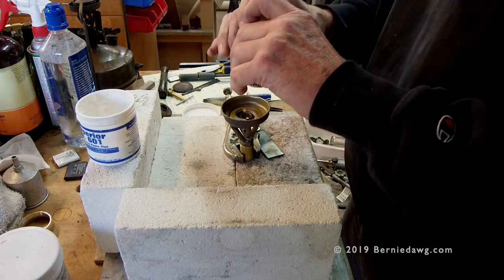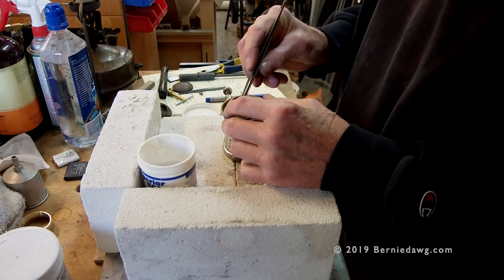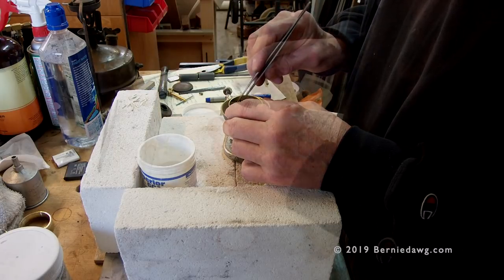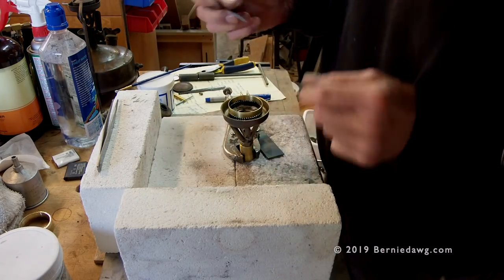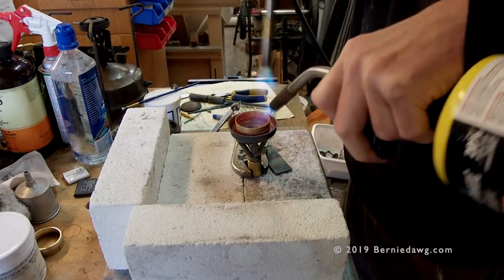I carefully placed the ring inside the burner bowl and used a small metric ruler to make sure it was centered. Then I took small cut pieces of brazing filler wire, dipped them in flux, and placed them along the bottom edge inside the ring. One last check for measurements to make sure everything was perfectly centered and aligned — you only get one shot at this. Then I grabbed a couple of torches, heated it up, and got the silver braze filler to melt and flow, holding the ring into the burner bowl.